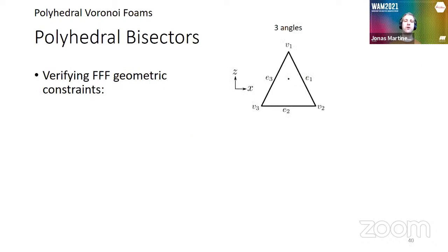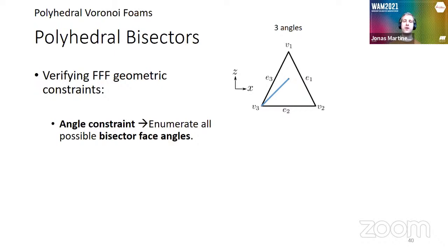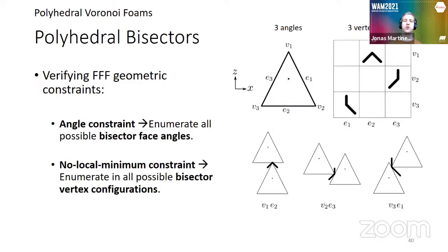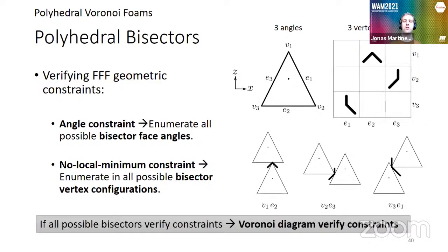So let's go back to the example of the triangle. Let's say we want to verify that our Voronoi diagram always satisfies the constraints. What we do is enumerate all the kinds of angles that the bisector can have. With a triangle, it's these 3 in blue. And then we also need to enumerate all the kinds of bisector vertex configurations. Actually there are only 3. So as you can see, this is a combinatorial problem. And we have a lemma that tells us that if all the bisectors satisfy these constraints, then the Voronoi diagram also satisfies these constraints. So we can prove that the Voronoi diagram is self-supported.